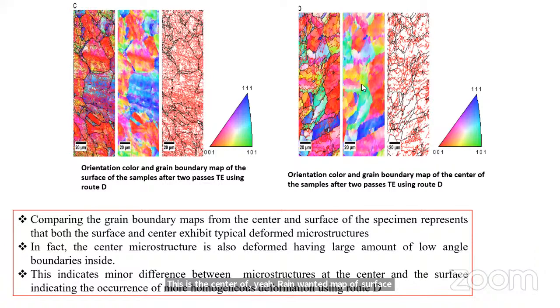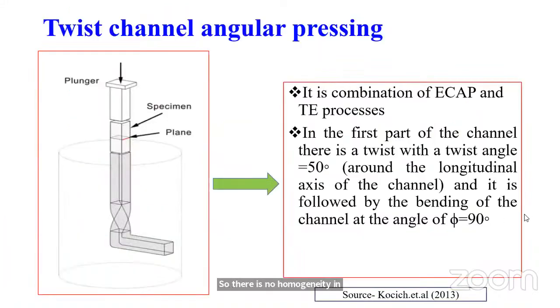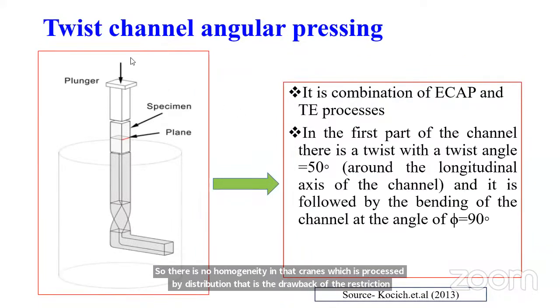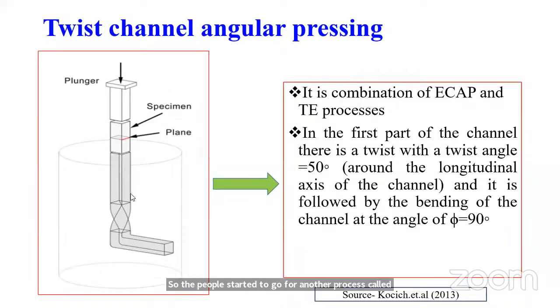These two diagrams give the difference between the EBSD color mapping taken at the surface and at the center of the samples. You can see there is a difference between the edge and the center of the samples. So there is no homogeneity in the grains processed by twist extrusion. That is the drawback of the twist extrusion process. So people started to go for another process called twist channel angular pressing, where they have imposed another deformation zone.